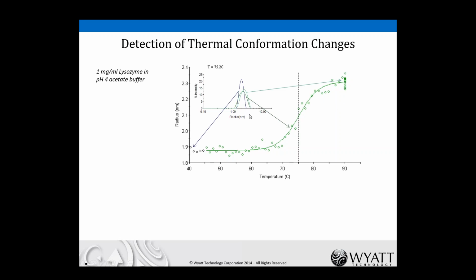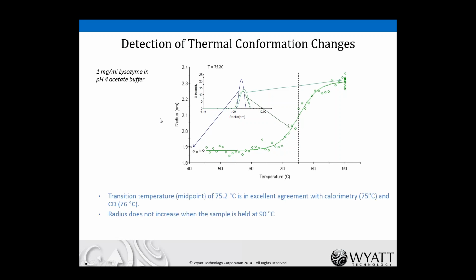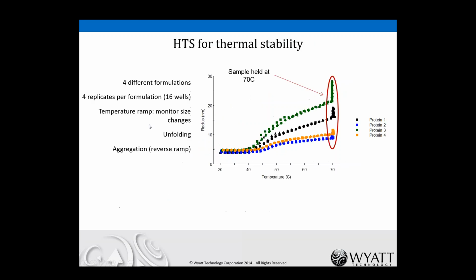And this shows the data that we get at all these intermediate points. Some nice sharp peaks down here at the lower temperature. There's a little bit of broadening, and that's because at any given temperature around unfolding, you'll have in equilibrium some folded and some unfolded material, and that will increase the width of the peak. All this shows up very nicely in the data. And these data agree well with calorimetry and CD, which also look at unfolding. This is perfectly reversible. You can cool it back down, goes back to 1.9.